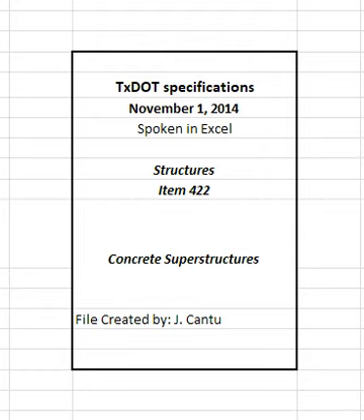4.6.6 Expansion joints. Construct joints and devices to provide for expansion and contraction in accordance with plan details and the requirements of this section and Item 454, Bridge Expansion Joints. Prevent bridging of concrete or mortar around expansion joint material in bearings and expansion joints. Use forms adaptable to loosening or early removal in construction of all open joints and joints to be filled with expansion joint material. Loosen these forms as soon as possible after final concrete set to permit free movement of the span without requiring full form removal and avoid expansion or contraction damage to the adjacent concrete.